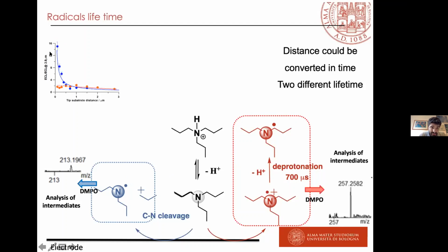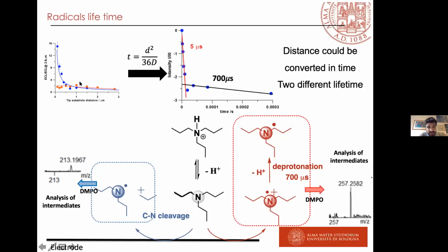But if we have higher intensity in close proximity, we should have a radical more reactive with a smaller lifetime. And in fact, if we go to the linearization of this curve, by measuring the lifetime, the traveling distance, what Bard called traveling distance, we measure the 700 microseconds, that is this mechanism, but also a short traveling distance that is, we think, and we have the proof from our analysis, the generation of the radical after CN cleavage of the amine.